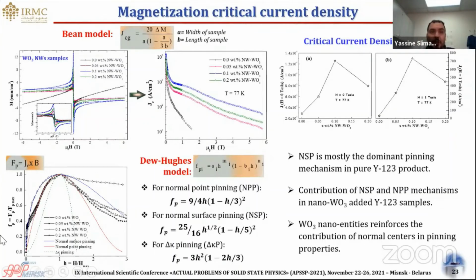Then we calculated the pinning force from the Jc measurement, and the plots are presented in this graph. Different pinning mechanisms were considered according to the Dew-Hughes model to explain the phenomena of pinning inside the superconducting materials. Here we found that over the applied field range up to this maximum peak, normal surface pinning is mostly the dominant pinning mechanism in the pristine YBCO compound.